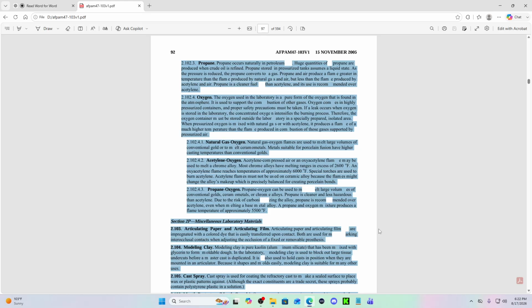2.100.4.2 Acetylene oxygen. Acetylene compressed air or an oxyacetylene flame may be used to melt a chrome alloy. Most chrome alloys have melting ranges in excess of 2,600 degrees Fahrenheit. An oxyacetylene flame reaches temperatures of approximately 6,000 degrees Fahrenheit. Special torches are used to burn acetylene. Acetylene flames must not be used on ceramic alloy because the fumes might change the alloy's makeup, which is precisely balanced for creating porcelain bonds.